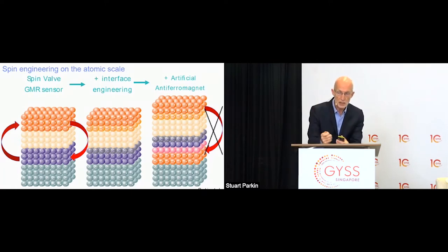I said we could build an artificial antiferromagnetic layer, as shown on the right, in which the blue layer is replaced with a sandwich of a blue and red layer separated by these pink dots, which is an ultra-thin layer of ruthenium, which gives rise to this long-range oscillatory coupling. But in this case, the thickness of the ruthenium, when it's very thin, gives rise to a very strong antiferromagnetic coupling. So we can build a reference magnetic layer whose net magnetic moment is zero, but the interface with copper is magnetized. And it turns out, I also showed that the phenomenon of giant magnetoresistance is dominated by spin-dependent scattering at the interfaces between copper, in this case, and the neighboring magnetic layers, which would be cobalt. So by spin engineering and creating an artificial antiferromagnet, by building structures with these layers, each of them just one or two atomic layers thick, we can build a structure which is unresponsive to these dipole fields, but can be responsive to external magnetic fields.